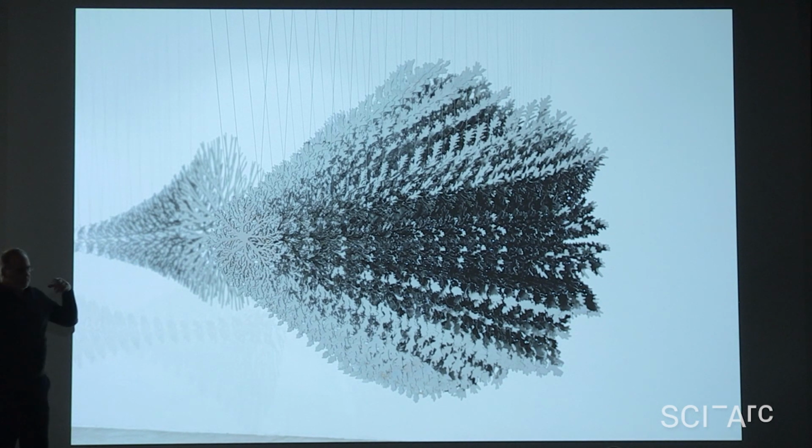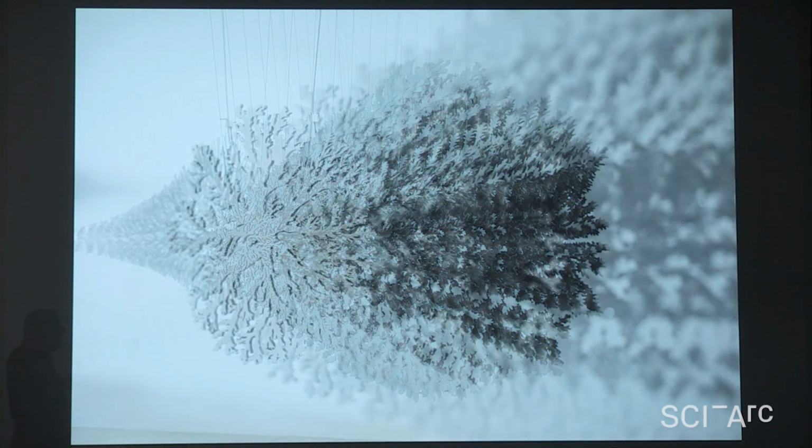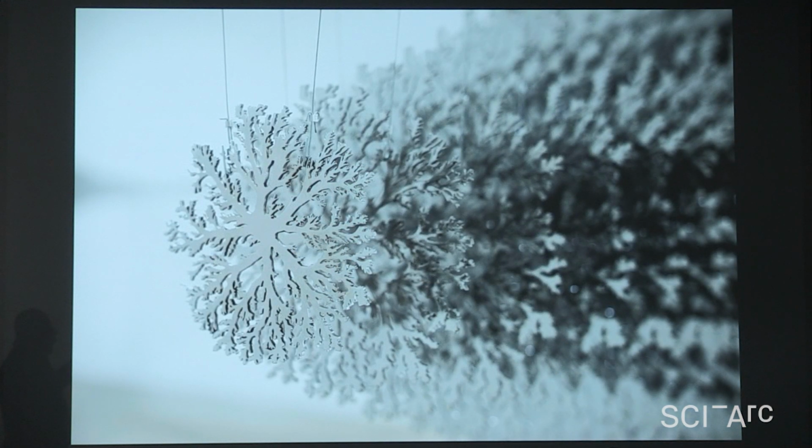Now, 5 years ago, you couldn't. These are laser cut. We have a laser in one of our plants. It's called a fiber laser. And 5-6 years ago, you could not cut this fine with a laser on a copper alloy or aluminum. They just didn't have the power or the wavelength. And the fiber laser today, super fast. If I did that little piece on the water jet, it would take about 8 hours. On the laser, it takes a matter of seconds. So it's very quick, but an incredibly accurate piece of equipment.